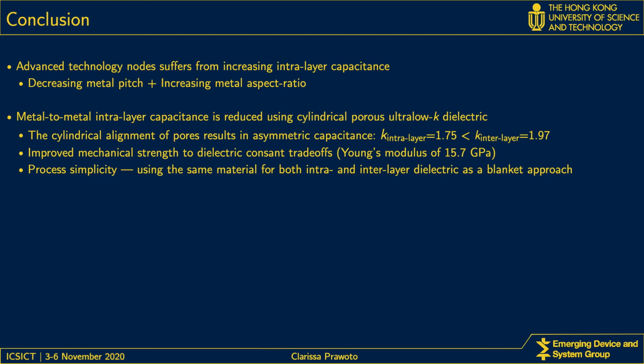We have also demonstrated that cylindrical porosity exhibits a superior trade-off between mechanical and electrical properties. This approach uses the same porous dielectric material for both intra and interlayer.